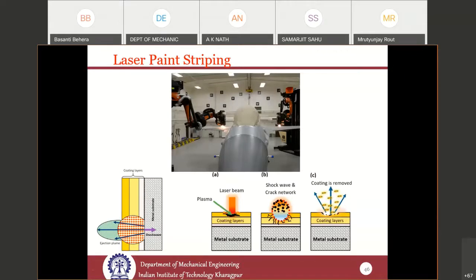These fatigue cracks or micro cracks may not be seen in the presence of paint on the surface. So after a certain number of take-offs and landings, all jet planes and aircraft are brought into the hangar, where the paint on the surface needs to be removed without damaging the metal surface. Here, the laser beam is used to remove the material.